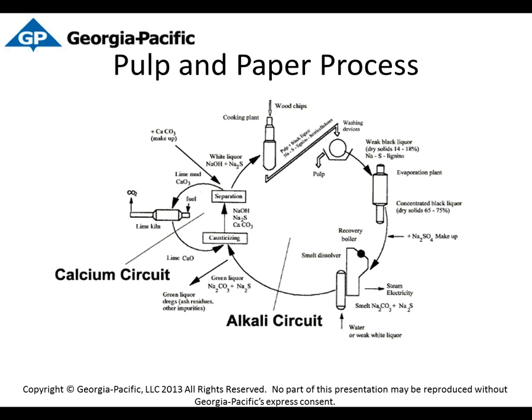So we have a range of pH from down to a 2 up to about 11 or 12. So you can be quite different extremes of environments, and then temperatures ranging anywhere from ambient temperature up to a couple of hundred degrees. And through all that, we've seen microbes almost in every stage of the process. So it's been a real eye-opener to what kind of environments these guys can live in and the damage they can cause.